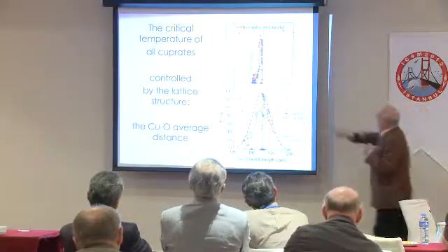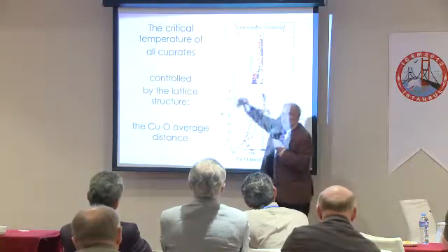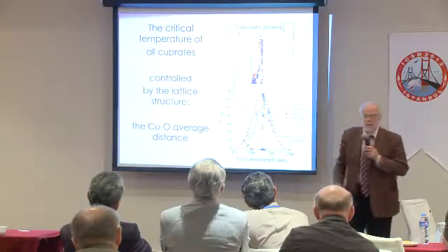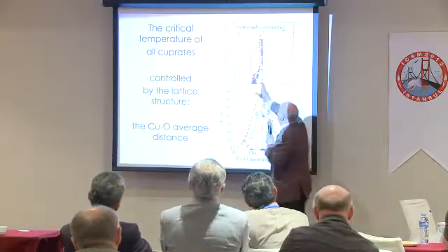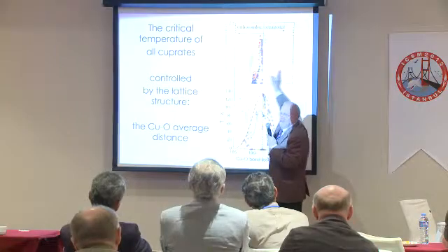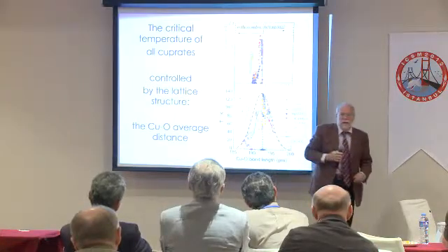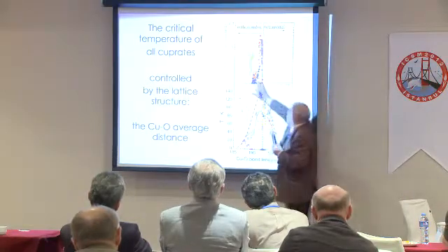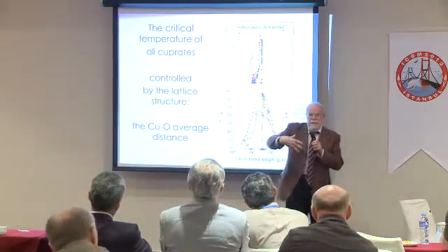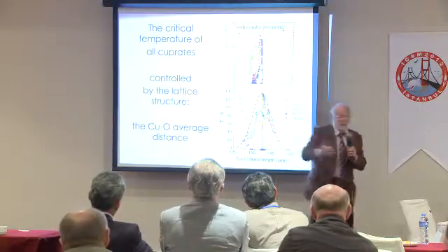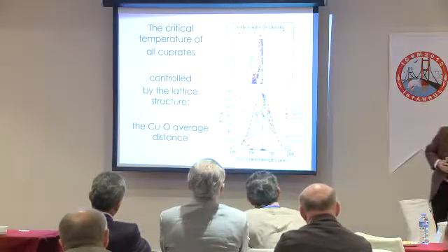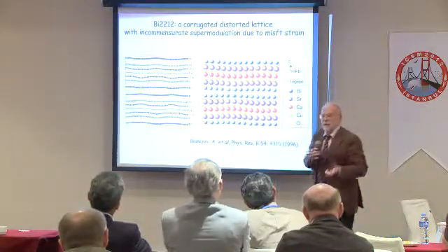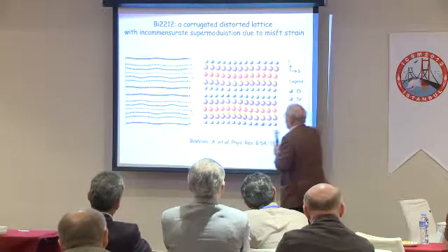And when you plot this, then you also have to look at the lattice. Is the lattice tetragonal or orthorhombic? Any kind of orthorhombicity. And you see that exactly at the point of maximum Tc, you have a broken symmetry from tetragonal to orthorhombic lattice. It can be in the copper-oxygen diagonal, but don't look like it. Why? Because the misfit broke not only the local symmetry, but also the long range symmetry. What does the misfit strain do? Misfit strain causes a corrugation of copper.